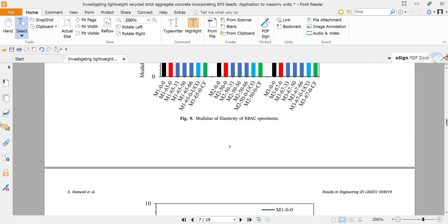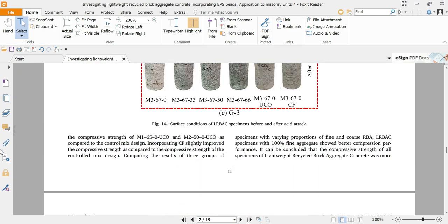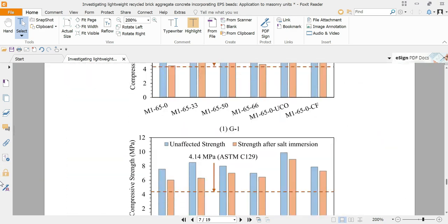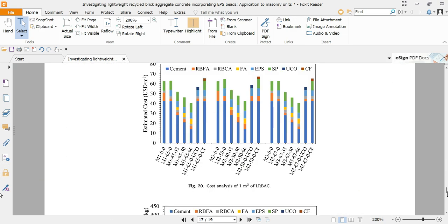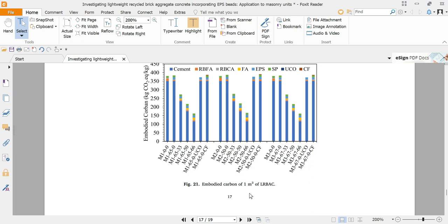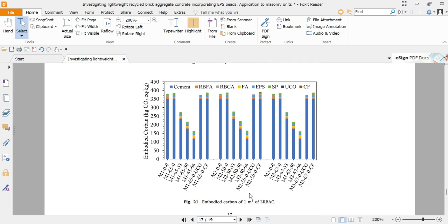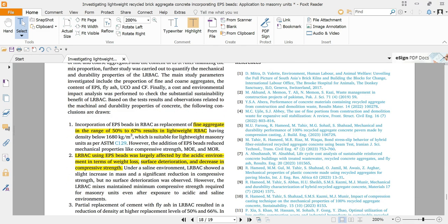So then I will jump to the conclusion of this study. We also performed some cost analysis as well as the environmental impact like the embodied carbon. So we also calculate the embodied carbon for this lightweight recycled brick aggregate concrete. Here we can see incorporating fly ash as a replacement of cement can significantly reduce the carbon footprint. So if we see the conclusion, we can see that fine aggregate replacement in the range of 50% to 67% can result in the lightweight concrete. So lightweight concrete means its density should be less than 1680 kilogram per meter cube.